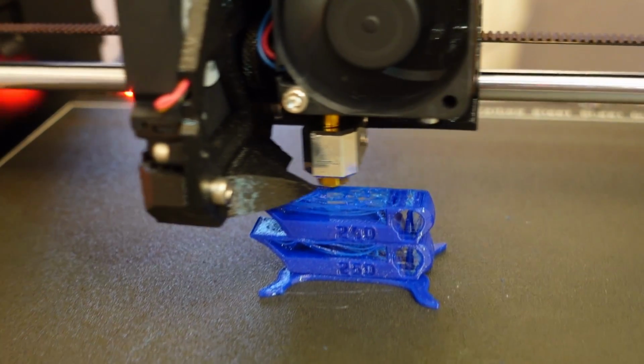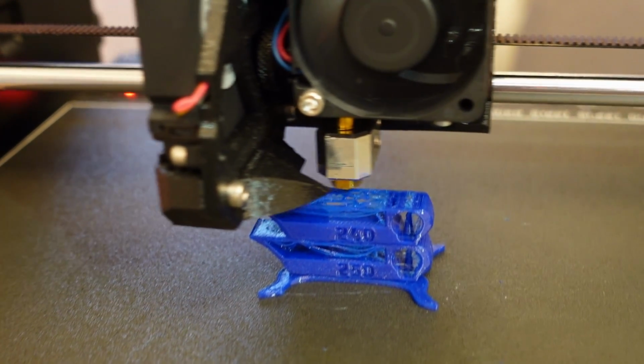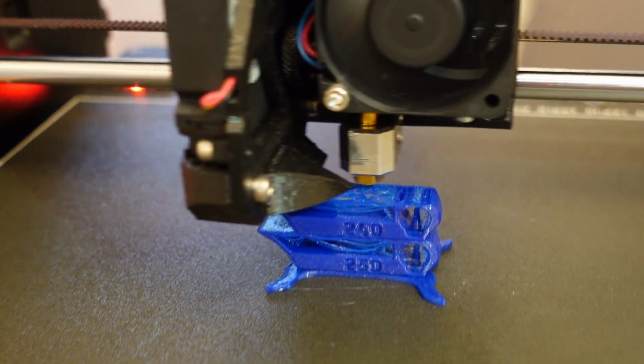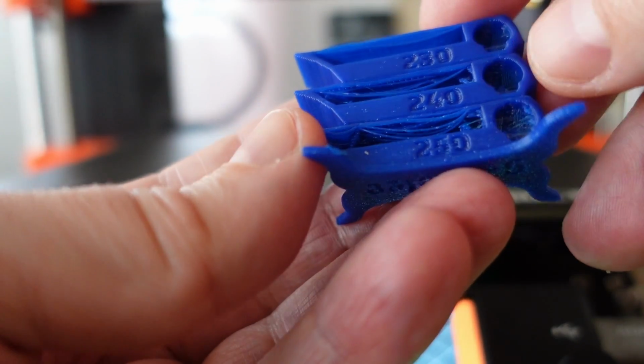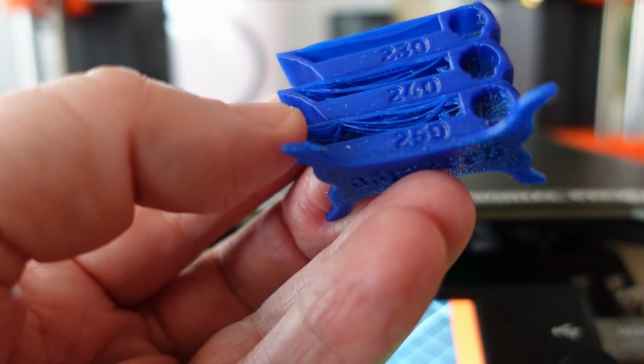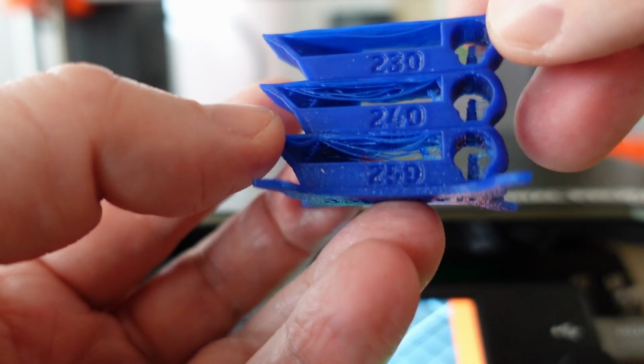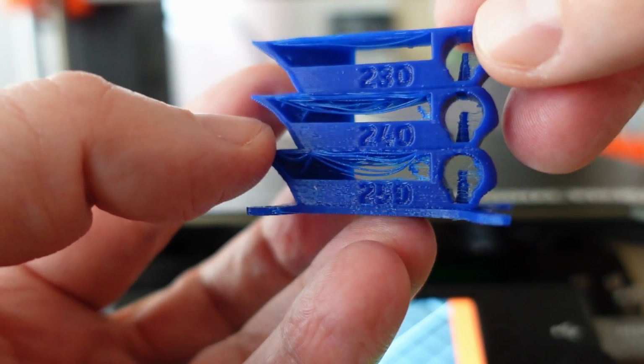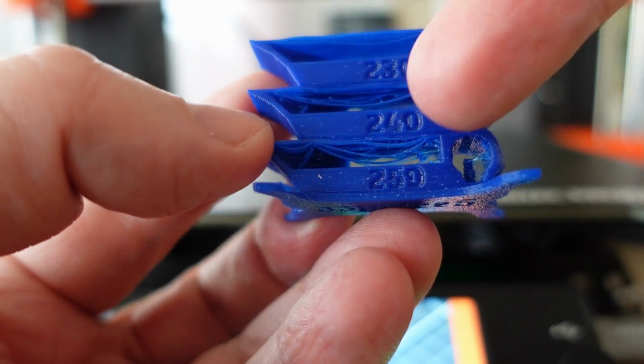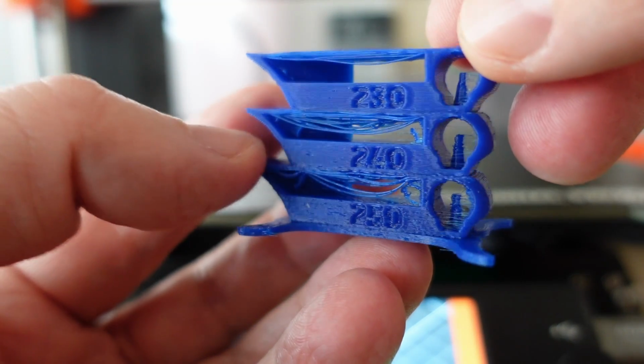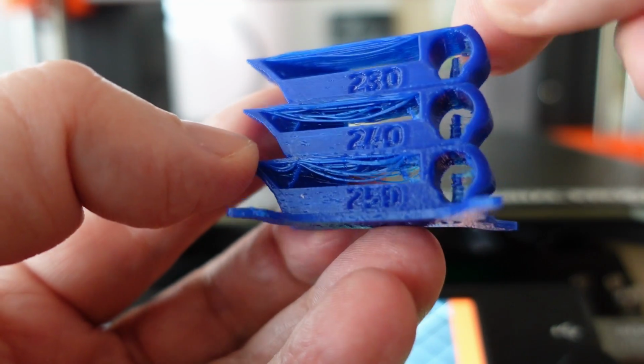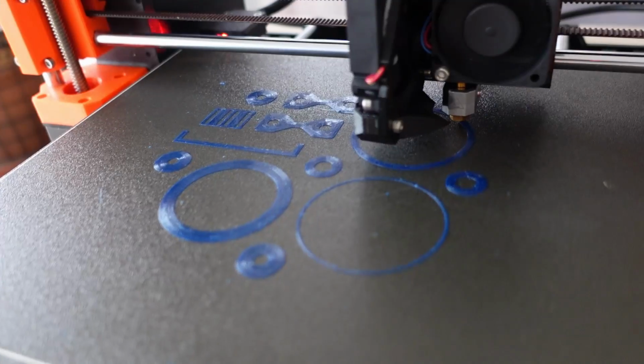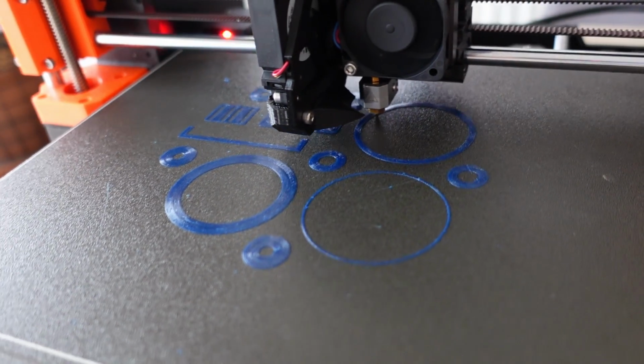The small bridging came out correctly. Great overhang and actually almost no stringing. So the only problem here is that bridging. But with the test specimens I don't have the bridging problem there, so I will again print everything on 240 degrees Celsius. The first layer is almost finished and it looks amazing.